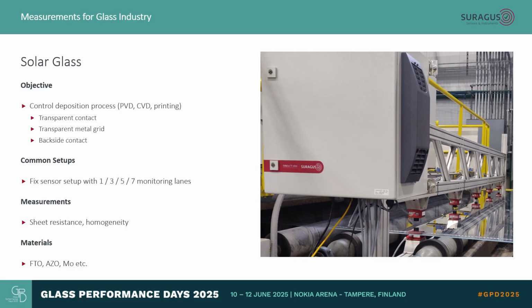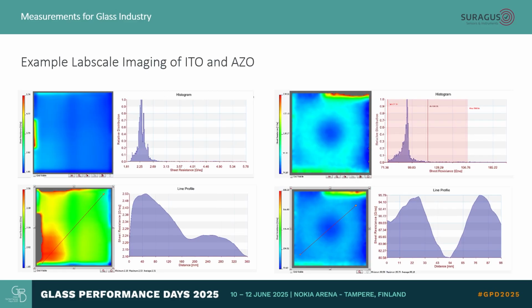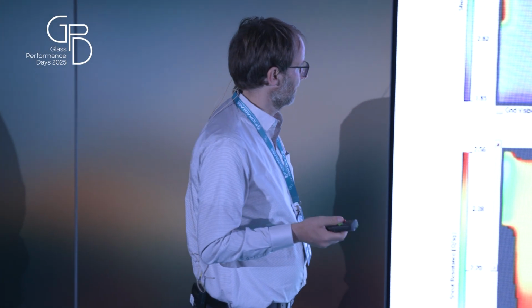Maybe we can come later to that. Eddy current is also able to image electrical performance. So this is kind of not a photo, it's basically a measurement. Each pixel is a measurement, and after a certain time, roughly 1 to 2 minutes depending on the size, you get such an image. And you can see process artifacts or process characteristics and improve homogeneity. Often it's about homogeneity and about finding the right level of sheet resistance. Not too much material, not too little, and having the right electrical performance.